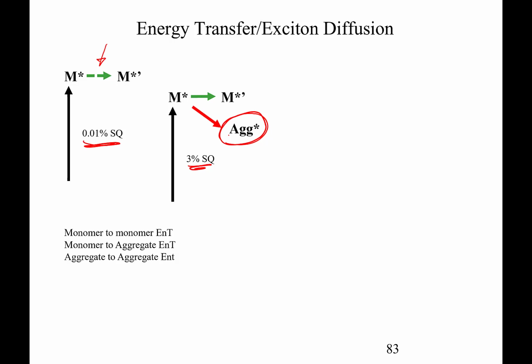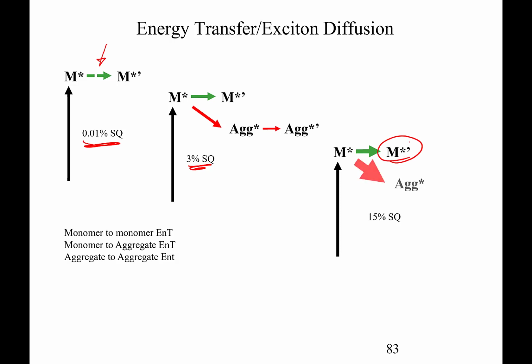We also recognize that there is this energy transfer within the aggregates. Now, when we get to the highest concentration of squaraines, 15%, we get a lot more energy transfer within the monomer, but we also get a large amount of that excited state energy that jumps directly into the aggregate. And of course, we also get this energy transfer, as we've demonstrated, within the aggregate state. It's very unusual, but it certainly tells us that that's why the devices work in the first place.